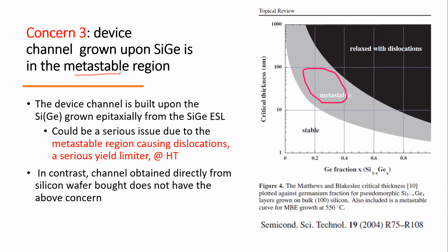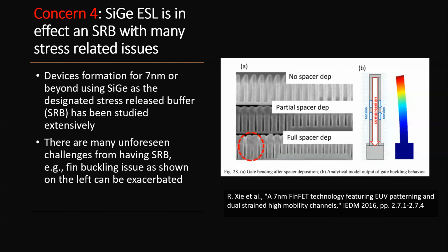The channel grown on silicon germanium is in a metastable region. It could be unstable and turn to relaxed and generate tons of dislocation if you're not careful with your high temperature need. Okay. Then concern 4 is that silicon germanium is an SRB, a stress release buffer or strain relax buffer. A lot of people try to introduce that for the 7 nanometer node, such as Samsung and IBM. So they use a silicon germanium buffer, and then on top of that grow a nice channel.